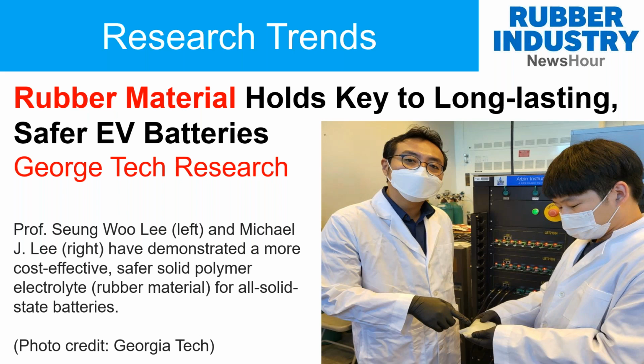This rubber electrolyte can be made using a simple polymerization process at low temperature conditions, generating robust and smooth interfaces on the surface of the electrolytes. These unique characteristics of the rubber electrolytes prevent lithium dendrite growth and allow for faster moving ions, enabling the reliable operation of solid-state batteries even at room temperature.